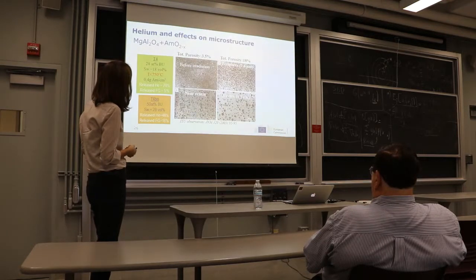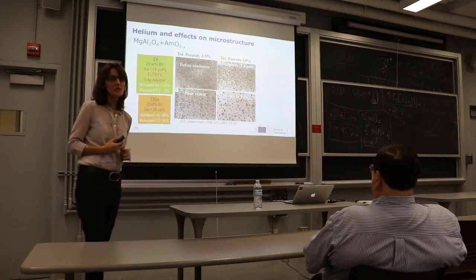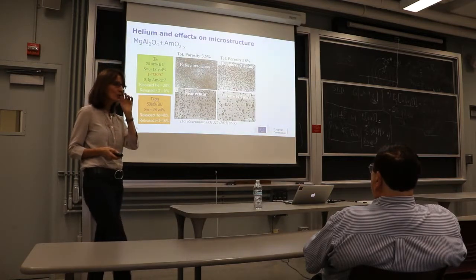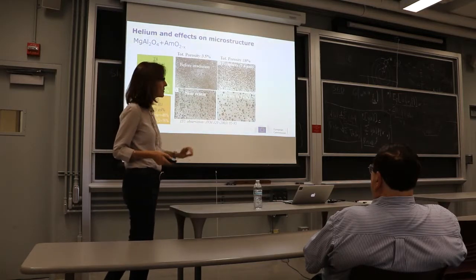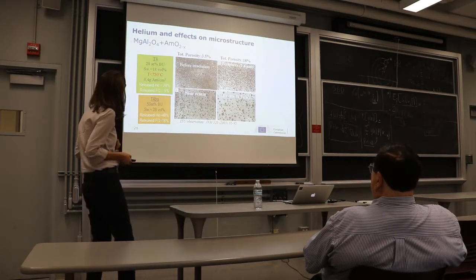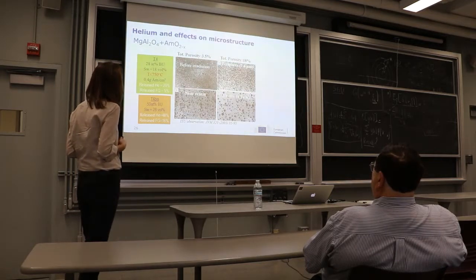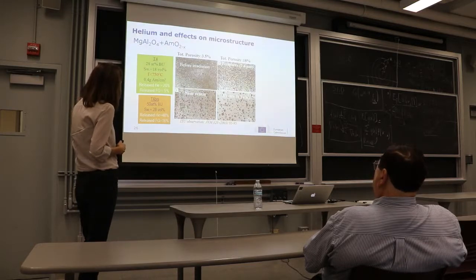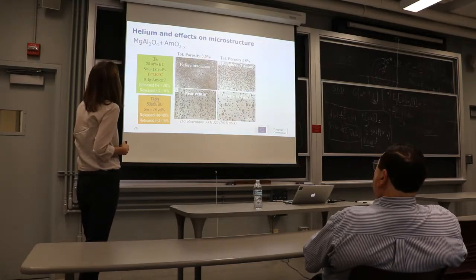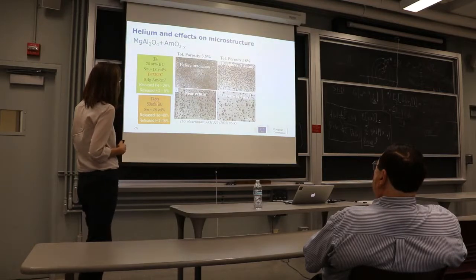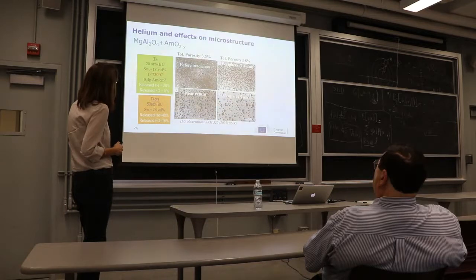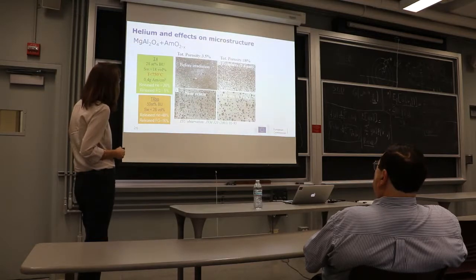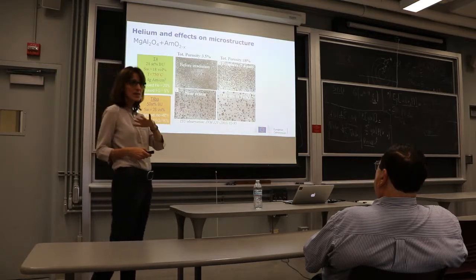And there have been different inert matrix fuels that have been selected, but they almost all show some common type of problems. And one problem, I've brought it here. This is the inert matrix, a mixed oxide, magnesium aluminum oxide, and the part that was irradiated is the americium oxide. Normally, when we fabricate this type of material, there is some porosity occurring in the material. These are the black dots that you see here. Plus, the white dots are the americium oxide, and the gray part is the inert matrix.